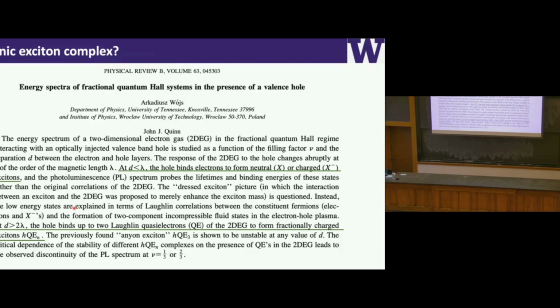In this particular theory, they consider a hole gas layer together with a 2D electron gas system. But they show that if the separation of this hole gas from the 2D electron gas is smaller than the magnetic length, then the hole will just bind to an electron to form neutral or charged excitons. So it means there's no fractional charge. However, if the separation D is larger than 2 times the magnetic length, then this hole can bind to Laughlin quasi-particles to form these fractionally charged exciton or trion states, okay? So that's the theoretical prediction.